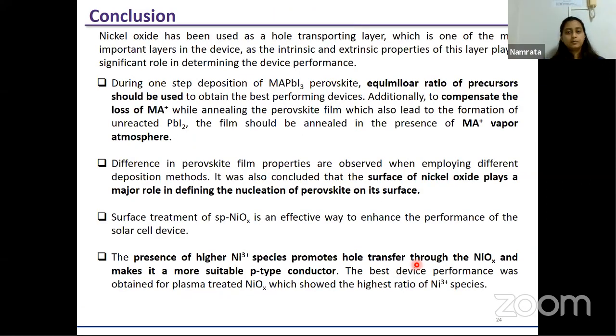So in total, from these series of investigations and the experiments that we did, we concluded that during the one-step deposition of lead iodide perovskite, equimolar ratio of precursors should be used to obtain the best performing devices. Additionally, to compensate the loss of MA+, that is methyl ammonium species, while annealing the perovskite film, which also led to the formation of unreacted PbI2, the film should be annealed in the presence of MA+ vapor atmosphere.